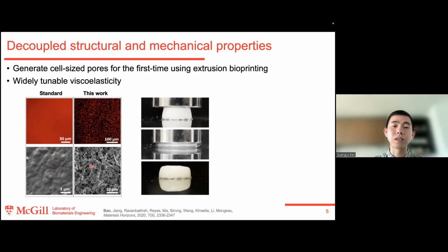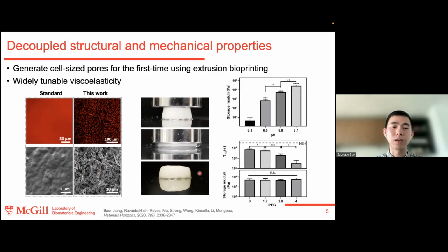porous and have interconnected pores, the hydrogels can be compressed, and the water can come out of them. After the release of the strain and the rehydration, they can resume their original shape. The stiffness of our hydrogel can be controlled using the pH. By tuning the pH within a very small window, we can tune the storage modulus from hundreds of Pascal to tens of kilopascal. So it basically covers the entire range of the stiffness of soft tissues.